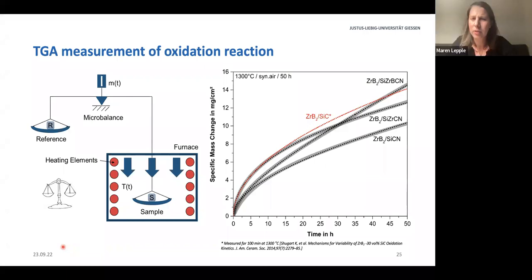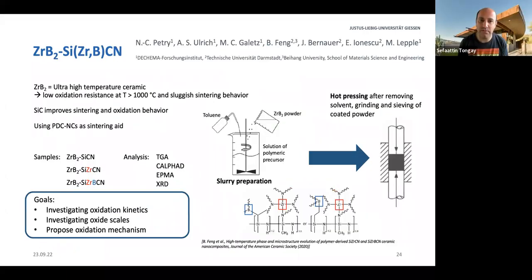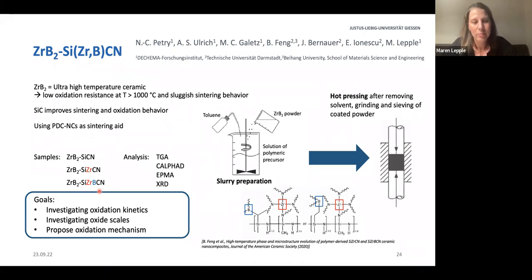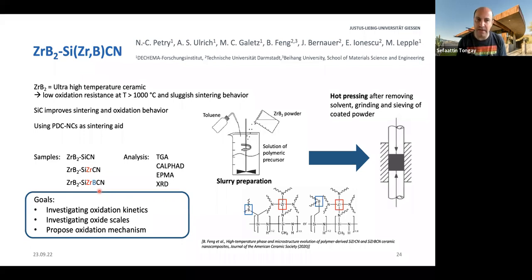Like which element? Can you remind me which one was that? Okay. So we had the zirconium carbonitride, and then we had zirconium and boron. And in the end, if you think about it, it's the same for zirconium boride: if you have zirconium in there and you oxidize it, you will form zirconia, and at higher temperatures, zirconia is an ionic conductor. But you have a mass loss during this reaction.